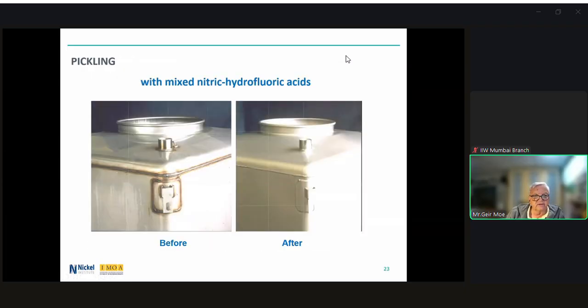But if the pickling is done appropriately, as in this case here, pickling of the weld seam on the top of the tank, we can see before and after. We have a nice clean stainless steel surface.